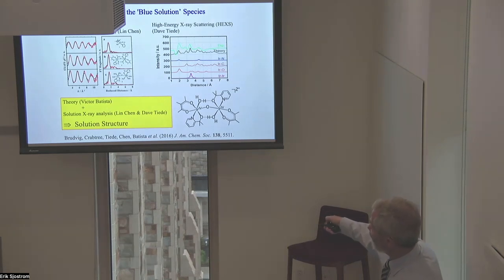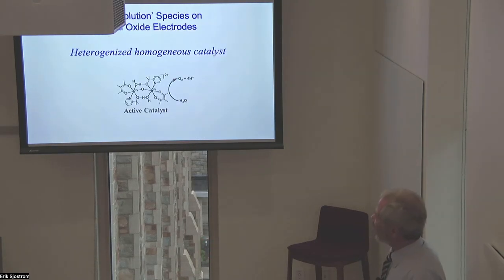The X-ray analysis was done with Dave Tiede and Lin Chen at Argonne National Lab using XAFS and high energy X-ray scattering, and computational modeling means you can show some of the modeled signals here. We came up with this structure, which is a diiridium monoxo bridge structure with these coordinating waters that can form internal hydrogen bonds that form a stable structure and leave open coordination sites that can presumably still be available for catalysis. So that is the catalyst.